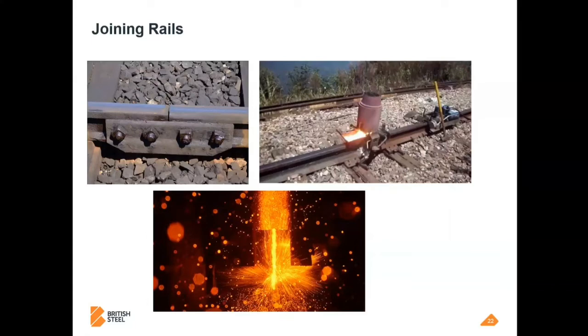But you fill that gap with liquid steel that's cast into there, and then you let it solidify, and you've joined the rails that way, and then you just grind it back to a seamless joint afterwards. That's very common. It's very portable. So it's dominant, really, because of its portability. And at the bottom is flash butt welding, which we'll talk a bit more about now.